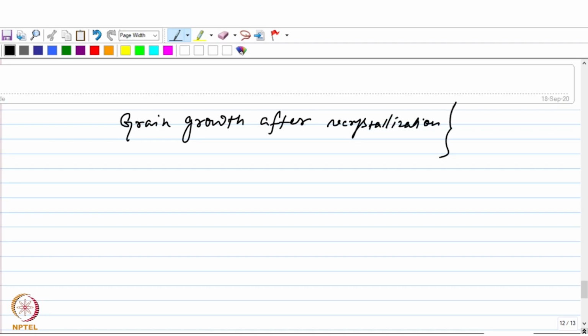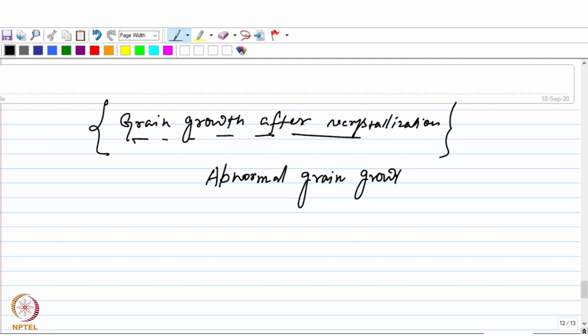So here we are talking about a scenario where all the grains are already recrystallized, right? Grains are all strain free, and we still continue to hold it. And as I said, if you do that, the grains will further grow and it can go to a very large extent, and it might lead to a phenomenon called abnormal grain growth. And this also goes by the name secondary recrystallization.